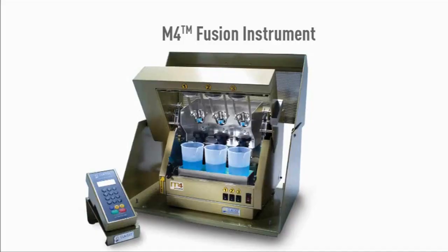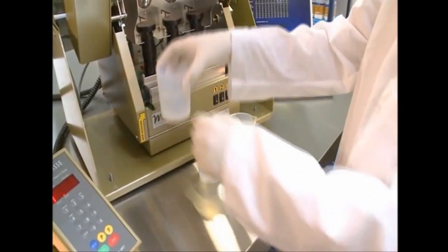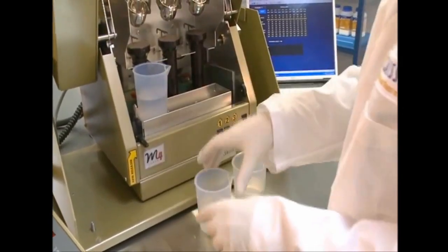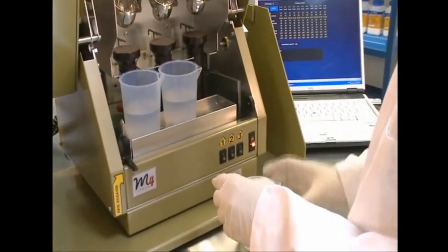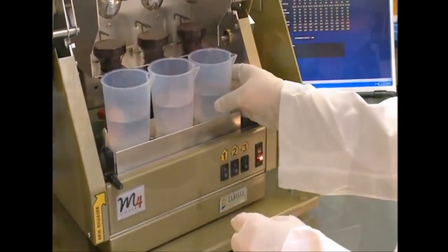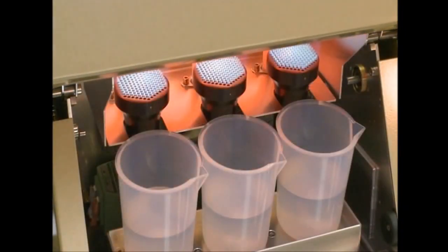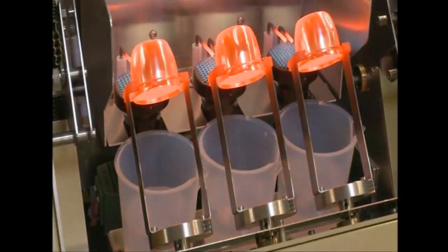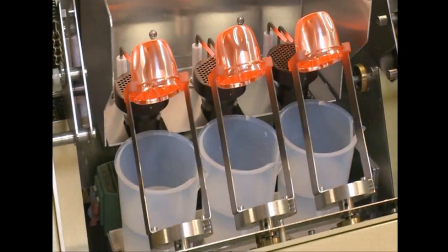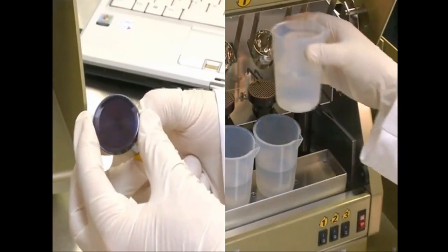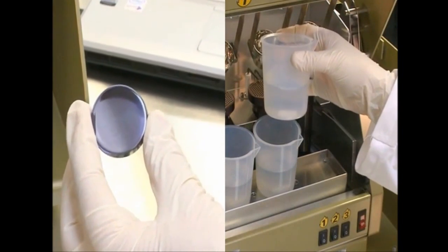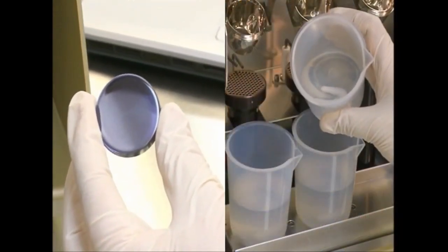Now, when you use borate fusion as a sample preparation method for ICP analysis, you simply mix the borate flux, 2 to 3 grams usually, the sample and any additive such as an oxidizer or a non-wetting agent, all within the platinum-gold crucible. Place the crucible on the fusion instrument. Instead of pouring the fused melt into a platinum disc as seen in the sample preparation for XRF, the fused melt is automatically poured into a diluted acid, and the magnetic stirring agitation is automatically started. Once the sample is completely dissolved, transfer it into a volumetric flask and adjust the final volume and acid concentration needed.